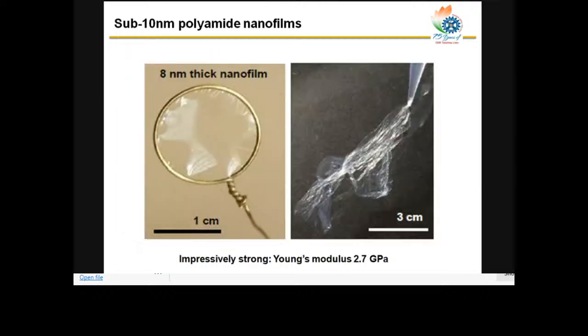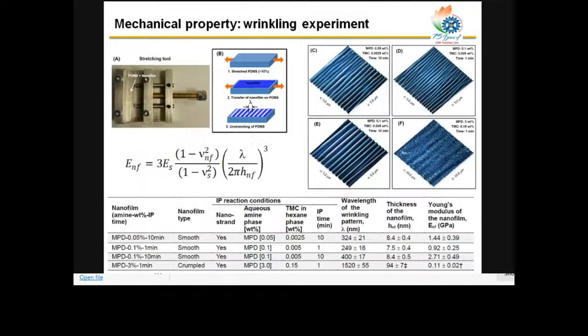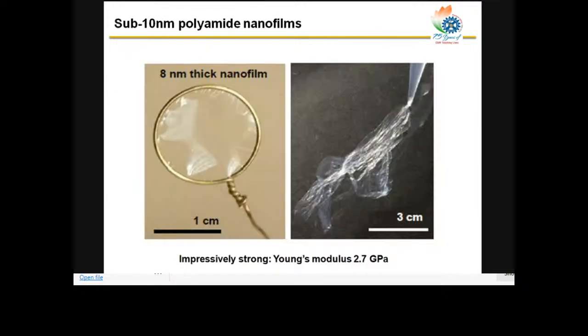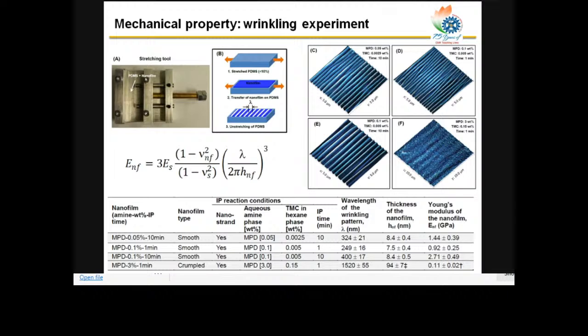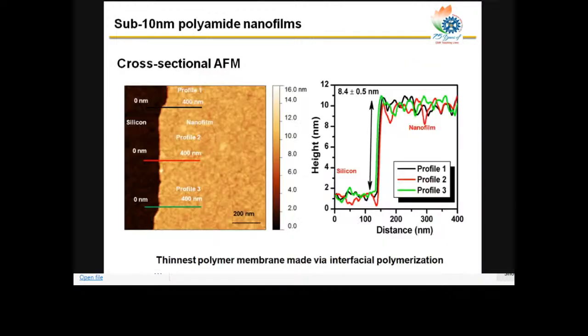Next. Yeah. So then we started measuring the thickness of this sub 10 nanometer polyamide nanofilm with AFM. Chirantan, please, the previous slide. Yes, thank you. So this sub 10 nanometer polyamide nanofilm is very difficult to measure the thickness of from this AFM image. So we took them on a silicon wafer and we scratched on the left side, you can see, to remove the polyamide. And under AFM, we started measuring the thickness from left to right. If you go from left to right, that means you are touching the silicon wafer. And then on the right, you will get a step profile to get the thickness of the polymer thin film.